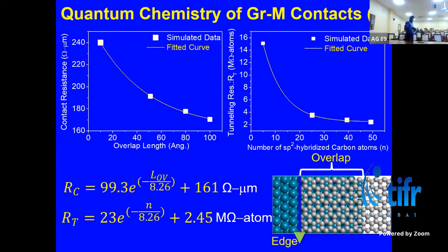So what we found was that the edge contributes 40% in terms of the conduction. Now, why is that? That basically made us think: why does the edge, where you have very few carbon atoms contributing to the conduction, compared to the overlap region, where you have quite a large number of carbon atoms contributing, contribute so significantly, right?